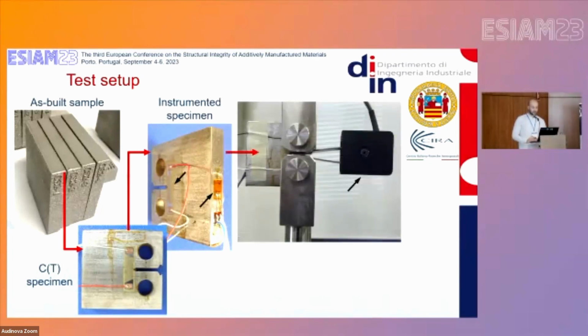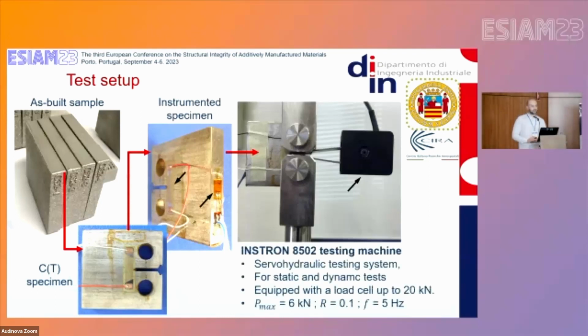This is a figure of the specimen that was ready to be tested. We can see also that we considered a clip gauge as a further element of comparison. The machine that we used to test specimens was a servo-hydraulic testing machine that can be used for static and cyclic tests, that was equipped at that time with a load cell of 20 kilonewton. The actual maximum load that was applied to the specimen was around 6 kilonewton, and the load ratio was 0.1.